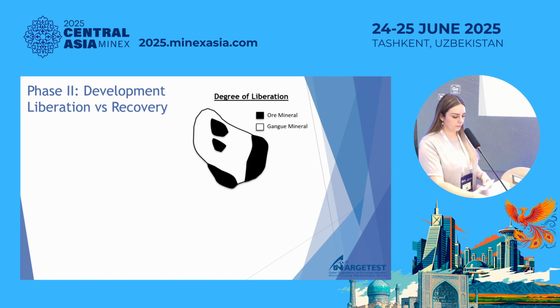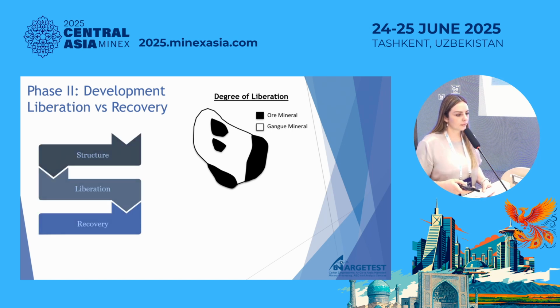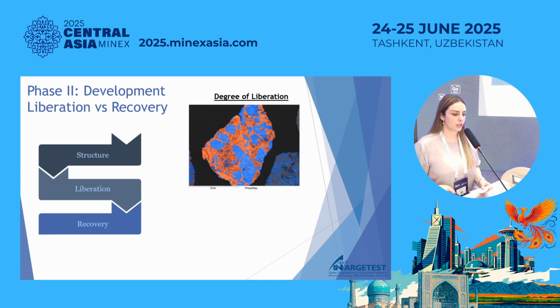Another powerful tool that can be used during the development stage is degree of liberation and liberation mineralogy. So run-of-mine consists of ore mineral that is surrounded by gangue. And degree of liberation tells you exactly how small you should be crushing your sample in order to have it completely free of the gangue material. Because no matter how efficient your flotation or your leaching process is, you cannot fully recover your mineral if it's interlocked by your gangue material. So it's actually structure that determines liberation that determines your recovery. Here's an actual picture from mineralogy.